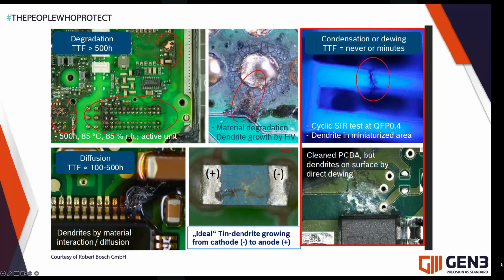Again, in the middle we see a capacitor where we've grown a tin dendrite across the top of the capacitor. And finally, the last one, again in a condensing environment, we can see the effect of what's happening with the leaching out of entrapped residues that are spilling out and being pulled out, and then resulting in a corrosion over a wider range, macroscopically, than just a fine dendrite.